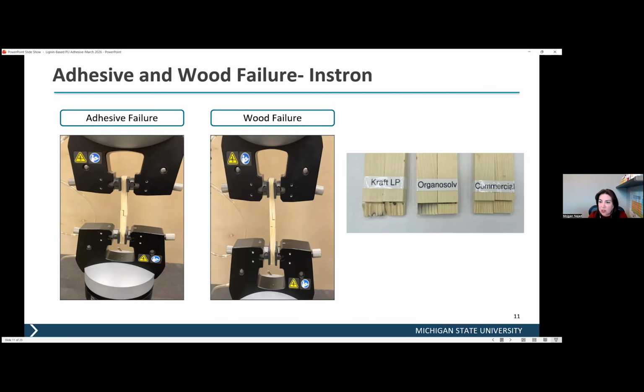You can see that this is a commercial adhesive. And then these two are made with the kraft softwood adhesive and organosolv wheat straw adhesive that we make. When that happens, you can see that the failure happens in the wood rather than the adhesive. And this is what we call 100% wood failure. And this is the criterion that we use.